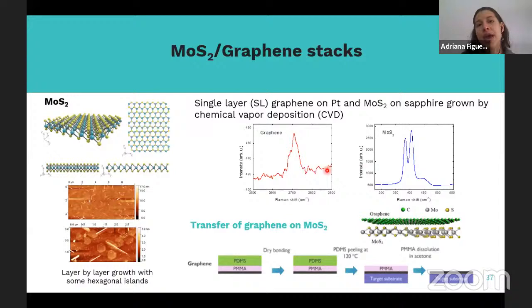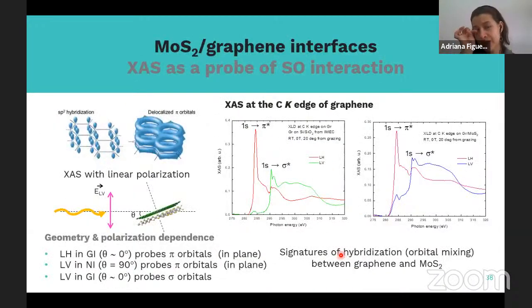That's what we did. We took graphene MoS2 stacks, where the different layers were grown by chemical vapor deposition, and then graphene is transferred on top of the MoS2. This was in collaboration with people from IMEC in Belgium. Then we took those samples to the synchrotron to study X-ray absorption spectroscopy. We studied two absorption edges on stacks of graphene without the MoS2 and with the MoS2. First I'm showing results at the K edge of graphene.